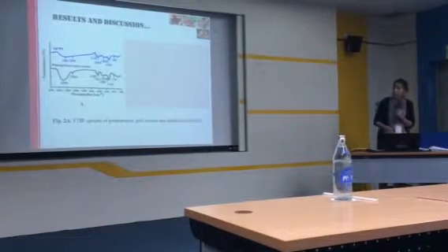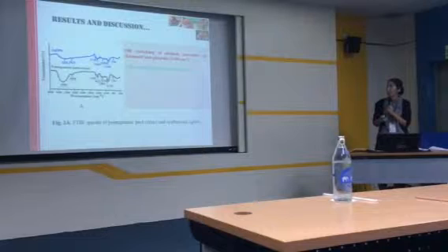Figure 2a shows the FTIR spectrum. The absorption peaks were assigned to O-H stretching of alcohol present in flavonoid and phenolic, C-H stretching of alkane, C=O stretching of amide in protein, aromatic amine, and C-N stretching of aliphatic. Moreover, the absorption pattern of silver nanoparticles and pomegranate peel was similar, suggesting that phytochemicals in the peel extract are coated on the surface of the silver nanoparticles.